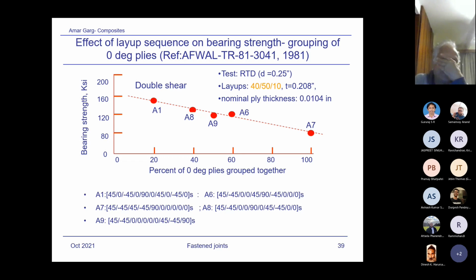I had observed this phenomenon myself when I was working at NASA. I designed a coupon and I did not worry about layup sequencing properly, and I found when I loaded the laminate, the fastener just pulled out like a plug, like a shear-out failure. So it's important to consider the joint design properly, the layups. It's very important.